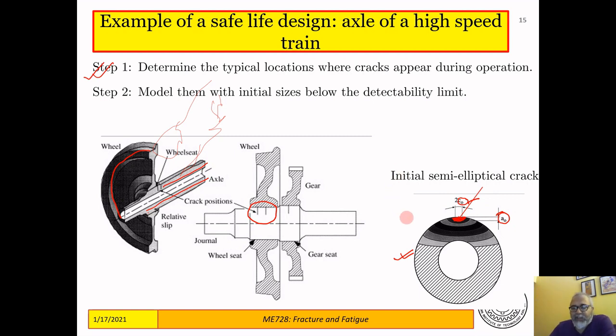So I start with this crack, and then I try to model how this crack grows through the material till it reaches the inner periphery, so that it becomes visible if I look in this direction. So how much time does it take to go through this thickness, if the initial crack size is this, and the initial location is as determined by my experience with axles? Now I can do this to wheels as well, and so the second step is to model them with initial sizes below the detectability limit.